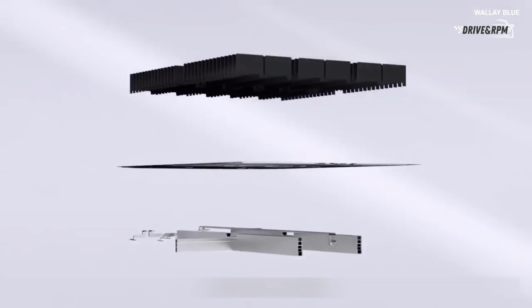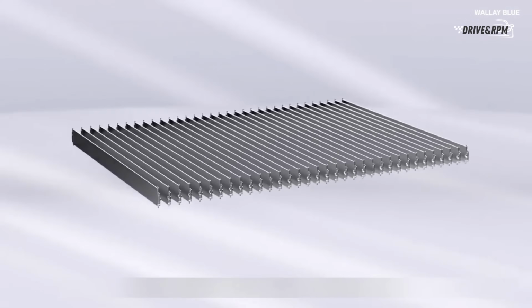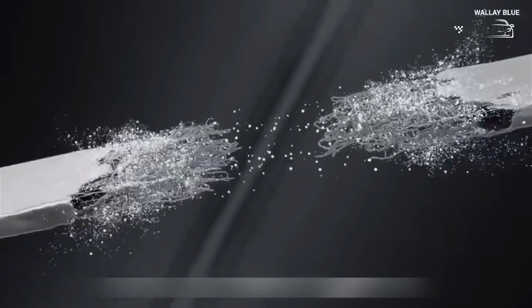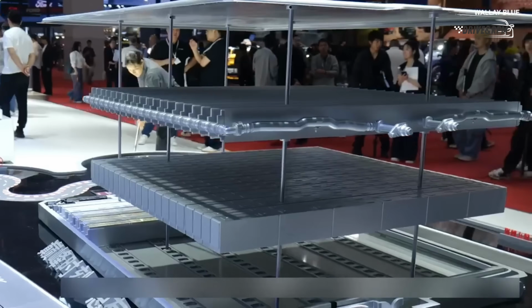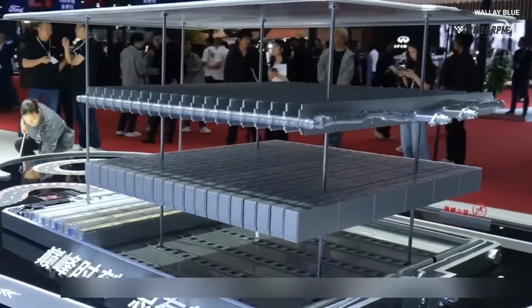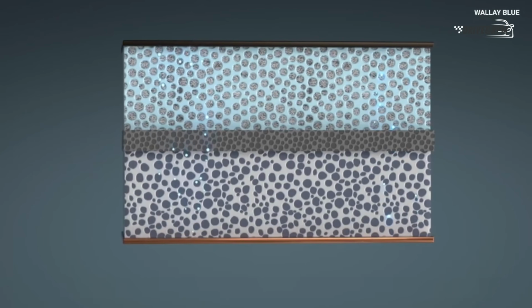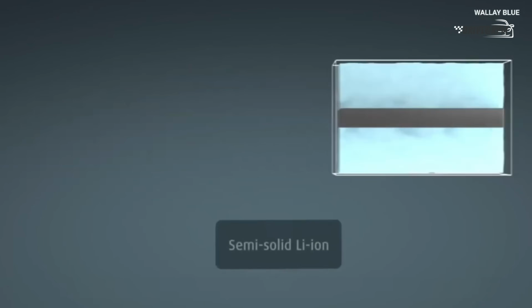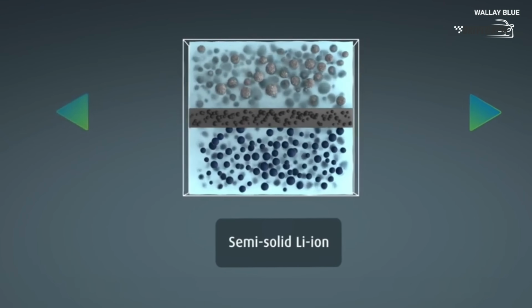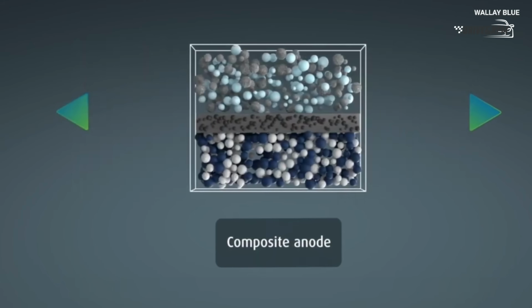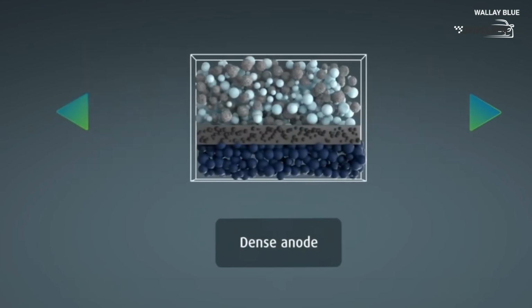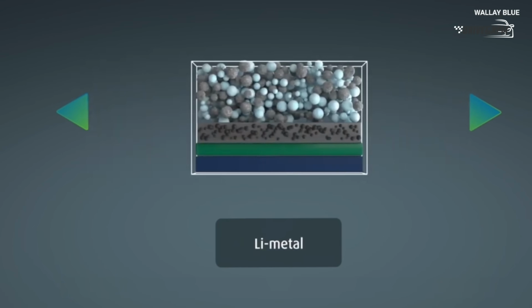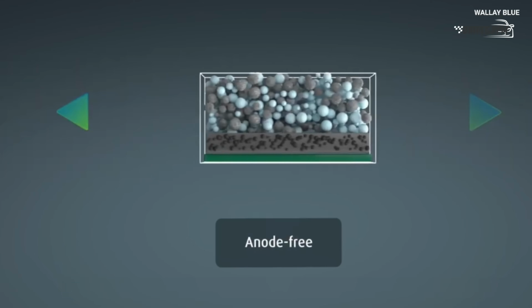It turns sluggish. Simultaneously, the charge transfer kinetics at the solid electrolyte interface, the SEI layer, plummet. Internal electrical resistance skyrockets. The real-world result: you watch your 300-mile range instantly drop to 170 miles. DC fast charging turns into a painfully slow trickle to prevent lithium plating, which could cause a short circuit.